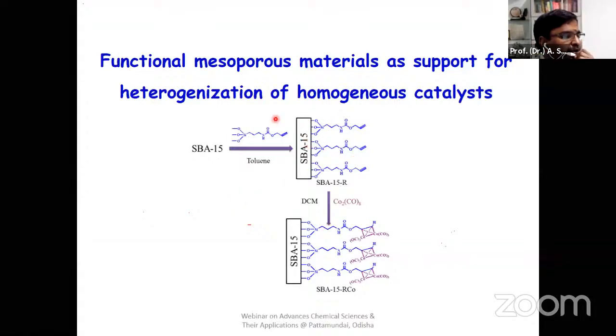This kind of molecular sieve material is one of the good catalysts which we have shown in the previous slide. And this kind of heterogeneous material is used for the anchoring of homogeneous catalysts. For example, cobalt carbonyl is one of the best commercial catalysts for the Otto Roelen process. If you have studied homogeneous organometallic complexes, you might know that cobalt carbonyl is one of the best catalysts for the hydroformylation of olefin.